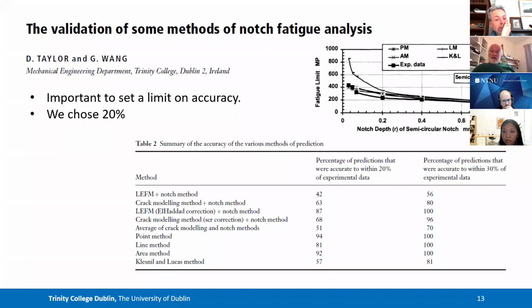But we did this, and then we used our theory, our critical distance idea, and then several other notch theories that were around at the time, which are all listed here in the table. And we looked at how accurate we were at predicting the fatigue limit values, the individual data points. And we're plotting these in a table.